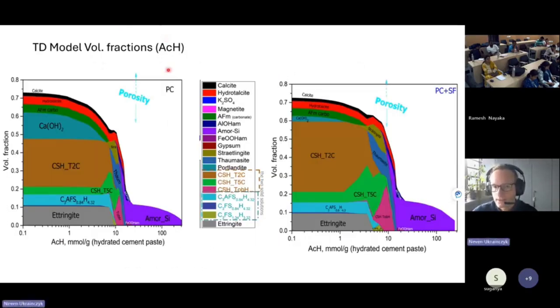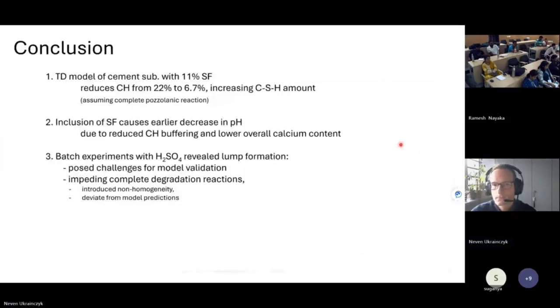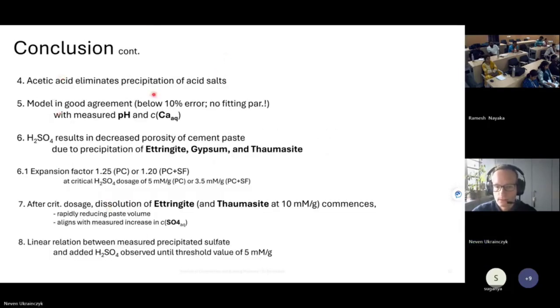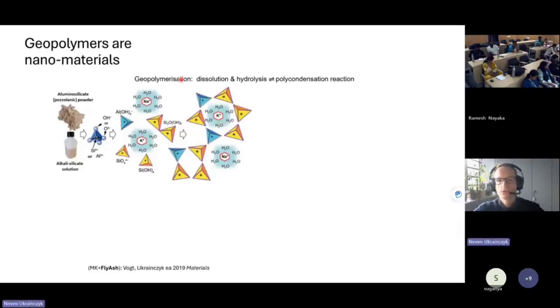These are the volume fractions with acetic acid, with Portlandite and Portland cement and silica fume. Again, less Portlandite. And you can see which phases are forming. You have thaumasite, strätlingite. Later it's dissolving. We have alumina gel precipitating here, and amorphous silica gel, also iron gel. Yeah, some conclusions. You can read this. There were some interesting conclusions. And now I will go to geopolymers.